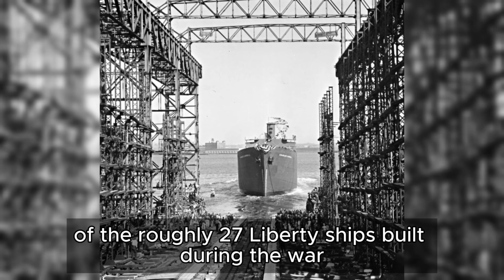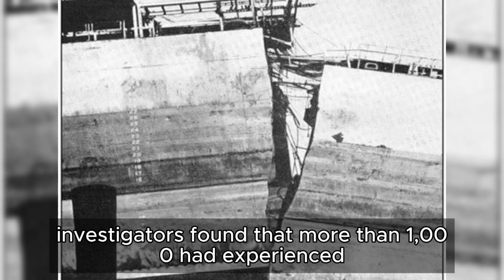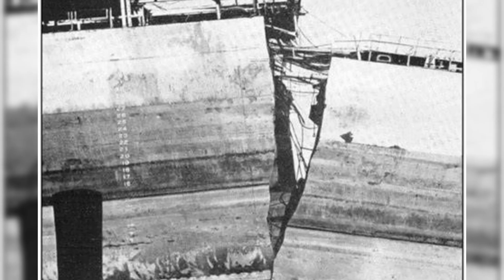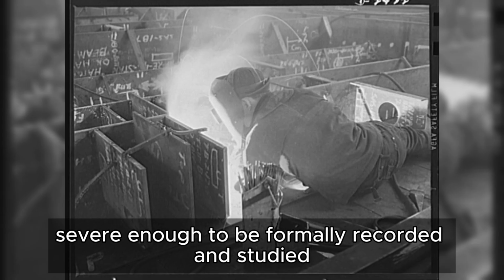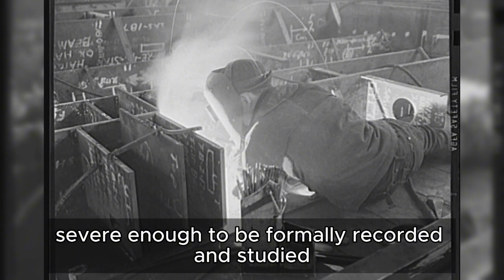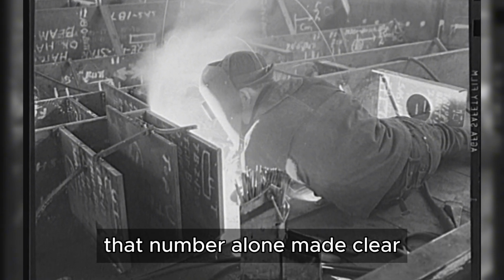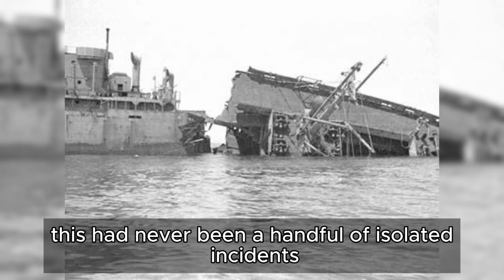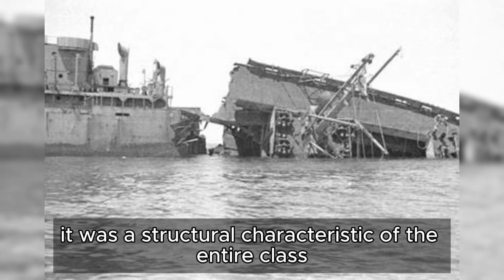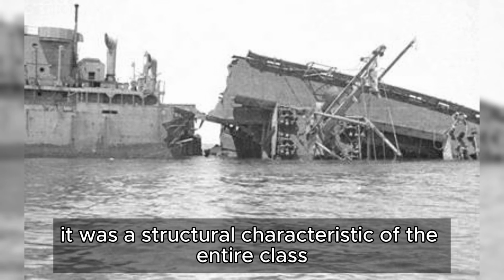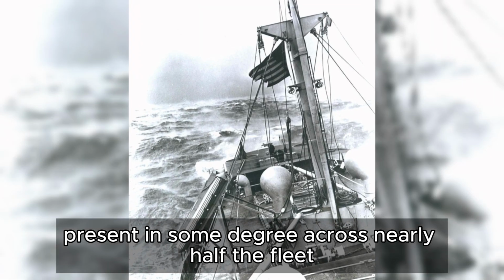Of the roughly 2,700 Liberty ships built during the war, investigators found that more than 1,000 had experienced significant hull cracking severe enough to be formally recorded and studied. That number alone made clear this had never been a handful of isolated incidents. It was a structural characteristic of the entire class, present in some degree across nearly half the fleet.